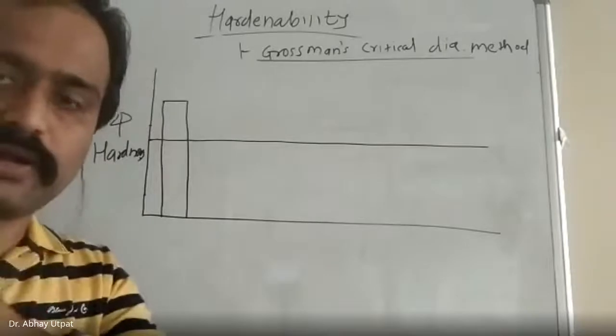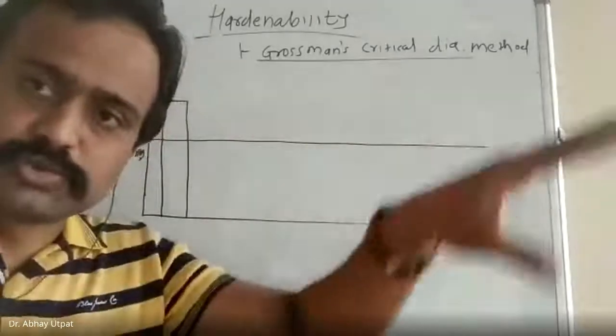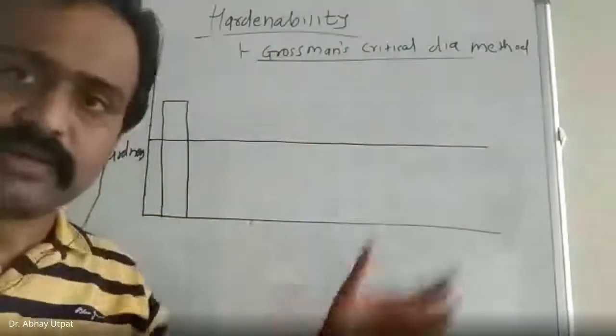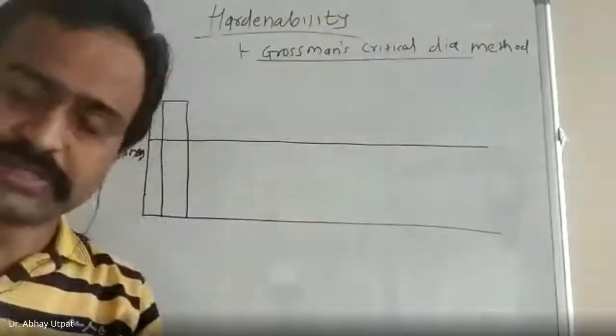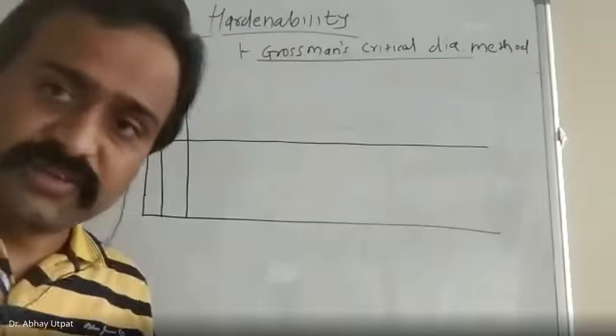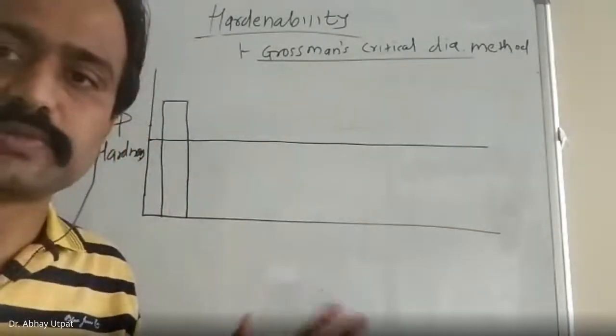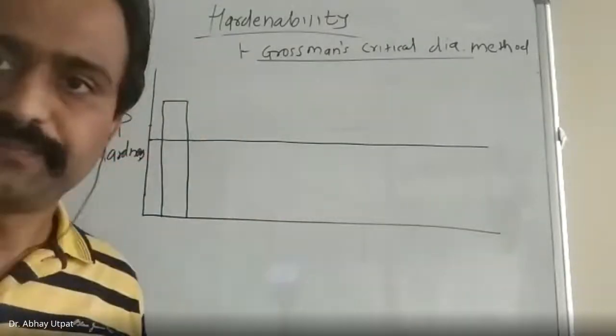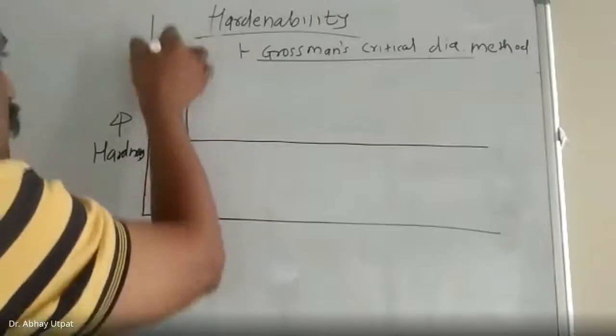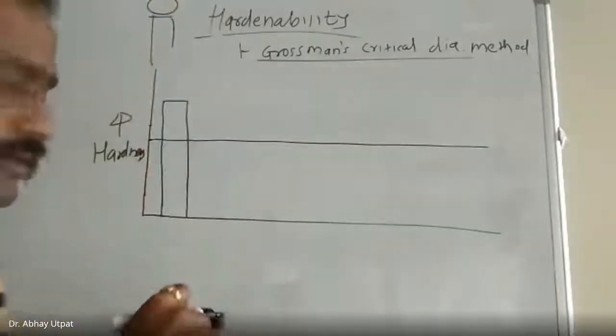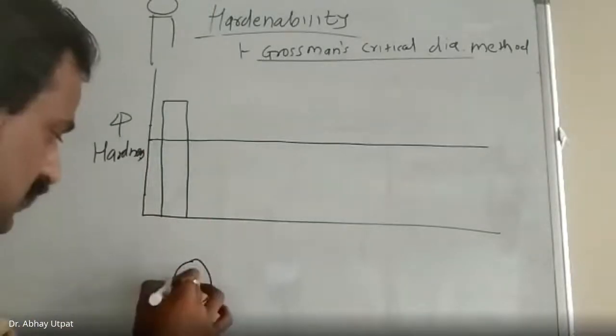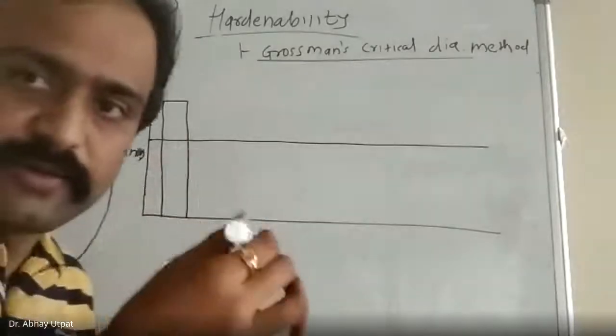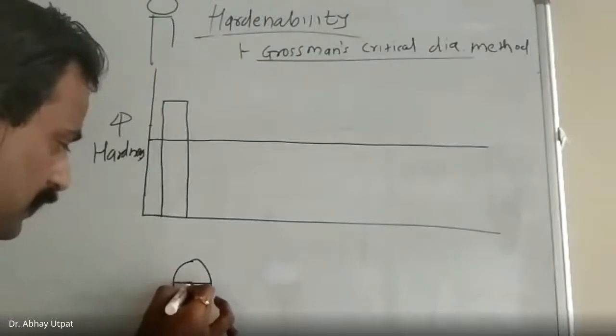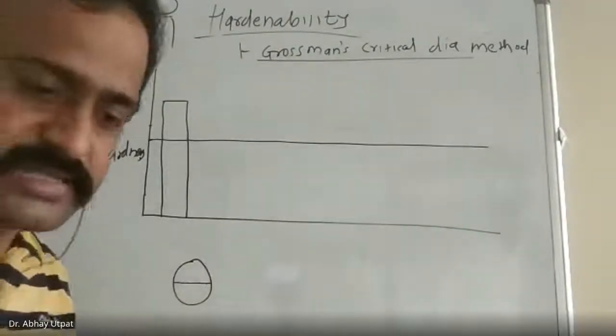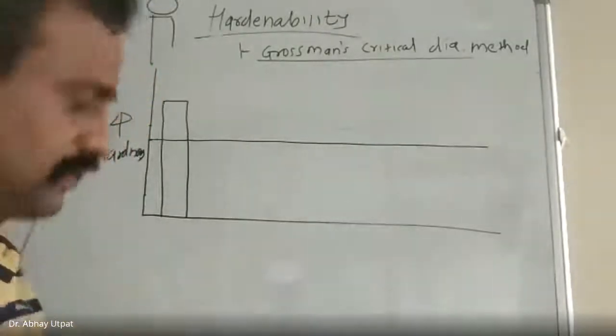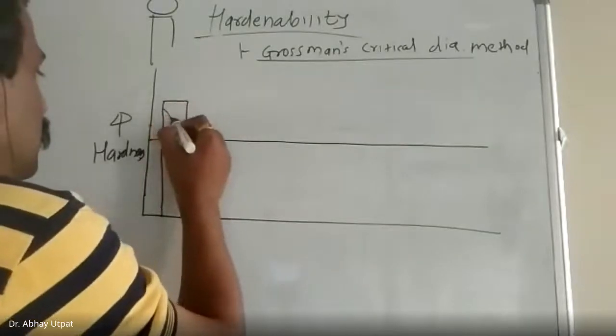Now this rod is made of the same material which is used by the customer for making his components. This bar I will take, heat, soak and quench in the quenchant which is used by the customer. After doing this, the hardness value is measured from the surface to the center. How? You have to take the cross section in this way and put your hardness tip, a diamond or ball indenter. So here 1, 2, 3, 4, 5, 6, 7, 8, 9, 10. At different points, hardness is measured, and that hardness is plotted here in this way.